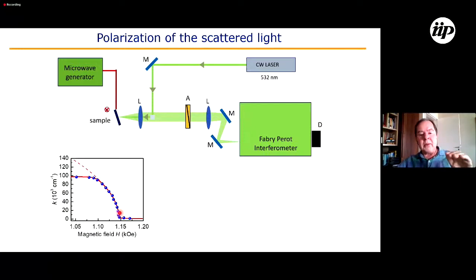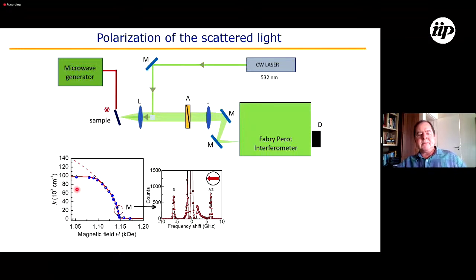If we had no coupling with phonons, the theoretical curve would be this dashed curve. But since we have coupling with phonons, the magnetoelastic dispersion will give this curve here, and we measure the polarization of the light in this region where the excitation is a magnon. And we have an analyzer before the entrance of the interferometer. The analyzer lets only one polarization come through.